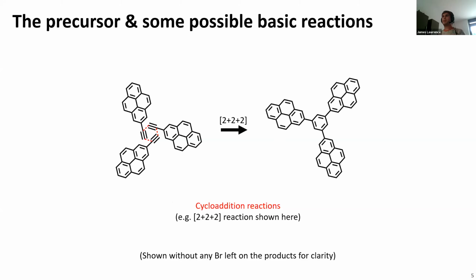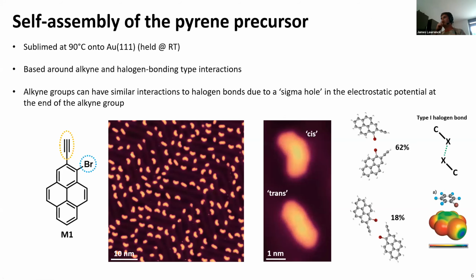So what we do is we sublime this molecule onto a gold 111 surface held at room temperature, and it self-assembles into some nice little dimers on the surface at a low coverage, which is about 0.3 monolayers.